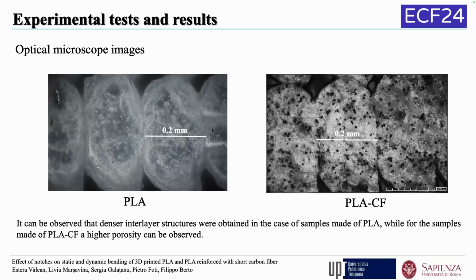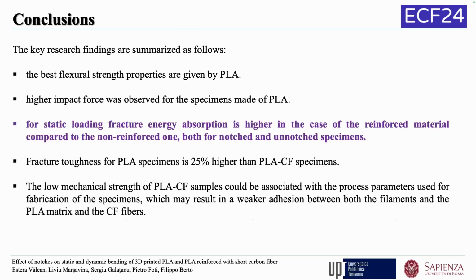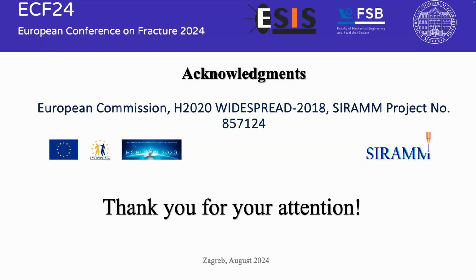And so looking at the micrograph of reinforced PLA, we can see around the fibers there are some pores, in the interlayer structure. So there is not a perfect bond on all the fibers, and this is probably due to the compatibility of the PLA, and maybe could also be due to our process parameters, fabrication parameters. We kept the same parameters for PLA and PLA reinforced with carbon fibers. So to conclude, the only improvement that we obtained by adding the carbon fiber was for the fracture energy, which was higher on static tests, not on dynamic tests. Thank you very much for your attention.